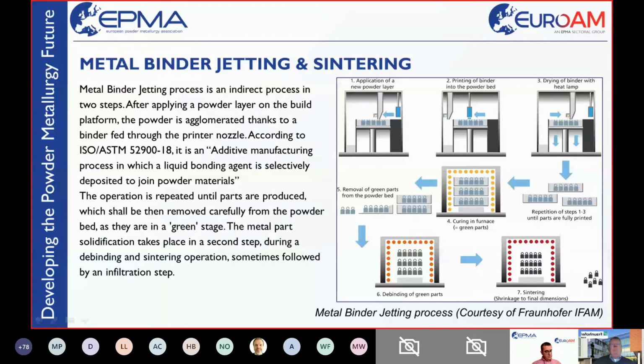There we do not have a beam melting powder, we simply have a printer printing a kind of binder. Here it's a liquid bonding agent in the standard, and this liquid bonding agent is selectively deposited to join powder materials. So no metal powder melted together, but in a first step bonded together.